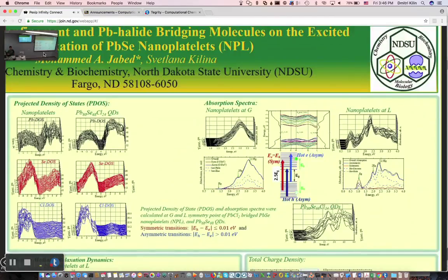But then why is it so? If you look at the bulk, where you apply the 3D periodic boundary conditions in all three directions, you probably would not expect your levels to be so discrete, right? This discreteness in your L point, well, I understand L is more discrete than gamma, but this discreteness probably will be significantly reduced if you have bulk, and here you have confinement in one direction.